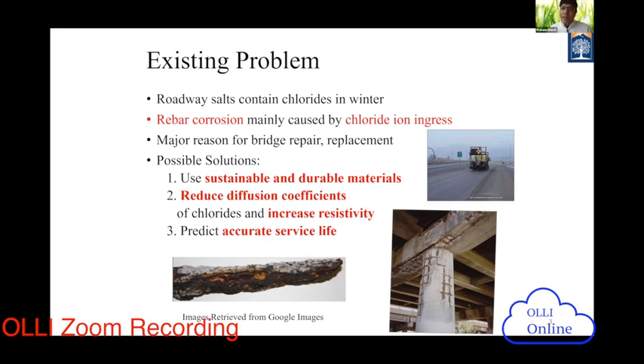So if you can reduce, basically delay, the diffusion process of chlorides and increase the resistivity. Resistivity is basically an indirect way of measuring chloride penetration in the concrete. So if we have higher resistivity and lower diffusion, then obviously the concrete will be a really good one, and it can delay the diffusion of chloride. So it will take a long time to initiate the corrosion.